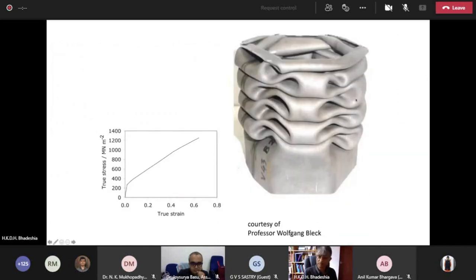And this is an example of a TWIP steel which has been tested in the same sort of scenario that I showed in the movie. Now, there is a problem here, which Wolfgang Bleck identified, and that is that the TWIP steel only absorbs sufficient energy after a large amount of strain. And a large amount of strain only happens in the most bent regions here. Whereas if you had a material which started off quite strong and had a stress-strain curve like this, then it would absorb much more energy.